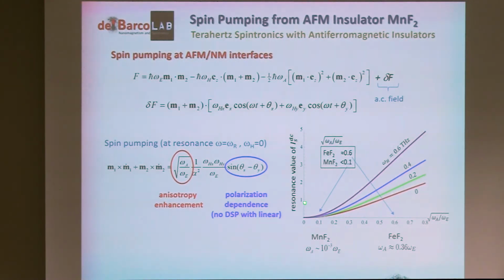And you can actually look here at the magnitude of the spin current that you will generate dynamically as a function of this parameter here. And you will place two different materials here or there. The iron difluoride has larger anisotropy, so the spin pumping is expected to be much larger than with manganese difluoride, although we still expect to see some, right? All right, so this is the contextualization of the experiments.